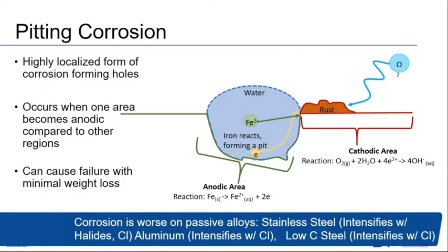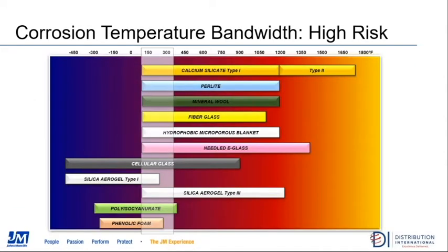So what is pitting corrosion? Pitting corrosion is a more localized form of corrosion. It occurs when one of the areas of the steel becomes anodic compared to the other regions. What we can see on that graphic there is that red line pretty much represents the surface of the steel. We see that rust on the top, and then we see that area with the water, and then underneath it, that pit that forms. So that pit is that pitting corrosion. What happens is that pit extends down into the metal, and this is where we can see failures occur with actual minimal loss to the steel itself.